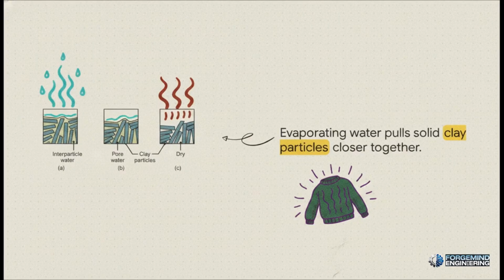To understand why that happens, let's zoom in to the microscopic level. In a moist green part, there's all this interparticle water acting as a tiny spacer between the flat clay particles. During drying, that water migrates to the surface via capillary action and just evaporates into the air. As the water leaves, those solid clay particles are physically pulled closer and closer together. It shrinks the entire part, kind of like how a wool sweater shrinks if you accidentally put it in a hot wash. We have to control the humidity and temperature absolutely perfectly until those grains finally make direct physical contact.